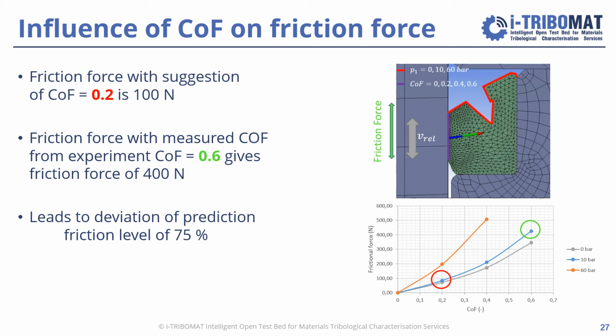So you see, the friction force increases steeply with coefficient of friction, and this difference gets even higher with higher chamber pressure, so more severe operating conditions. So even for moderate operating conditions of 10 bars, a wrong coefficient of friction leads to a deviation of your prediction level of friction of 75%. So you increase a massive uncertainty in your prediction of your target value.